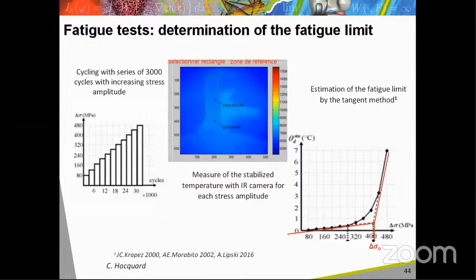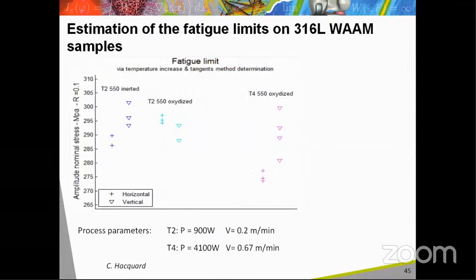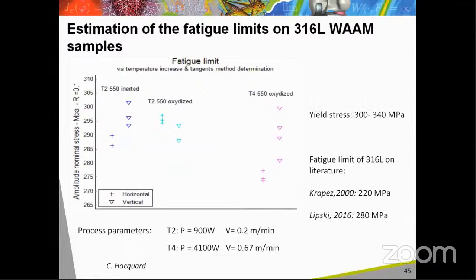The fatigue limits obtained with two WAAM process parameters on samples of 316L were compared. The fatigue limits in the build direction and in the horizontal direction were also compared. The obtained values for the fatigue limits are rather high compared to the yield stress of the material or compared to some literature data on 316L materials obtained by conventional routes.